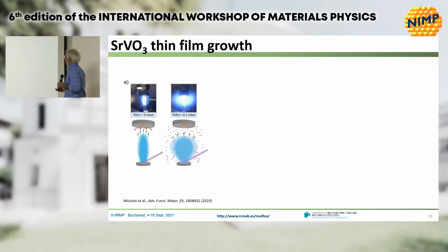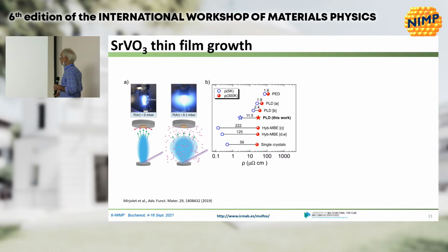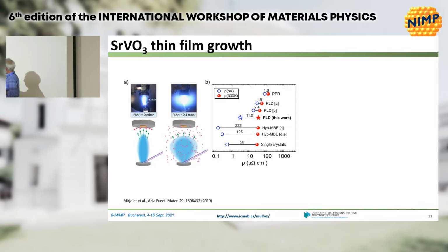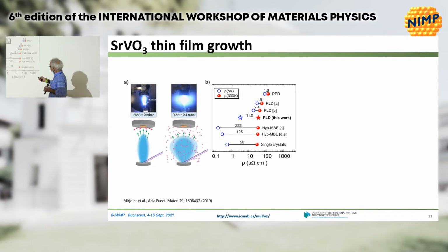And in that way, using this trick, filling the chamber with argon gas before starting the deposition, we managed to reduce the point defects and to reduce the residual resistivity. And you see that this is the value of resistance at the lowest temperature for the grown film. This is the room temperature, this is the low temperature. And you see that this number is much higher than previously reported. The resistivity ratio in our films is between 10 and 20, which is far from these points obtained by MBE, but definitely better than before.